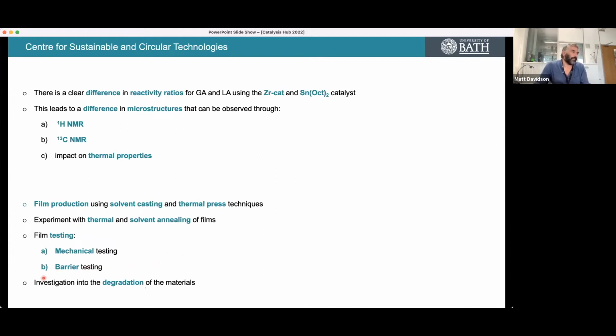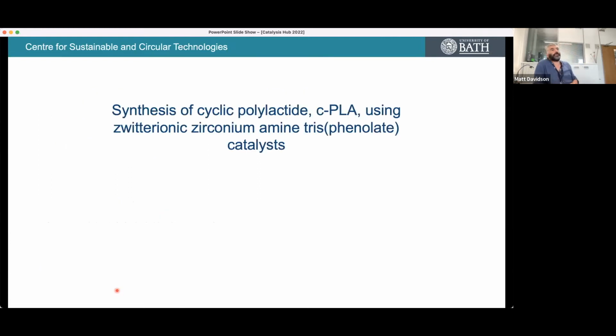And of course, the other thing where the properties of these two materials differ, where the glycolide is desirable and the lactide is not, is in degradation. So if we can use this to control the degradation of PLA, rather than just have the hydrolysis of polyglycolic acid, which is too great, and the hydrolysis of polylactic acid, which isn't great enough, if we can control this with the catalytic approach that we've got, then that will give us some interesting end-of-life options for the copolymers that we can potentially make.